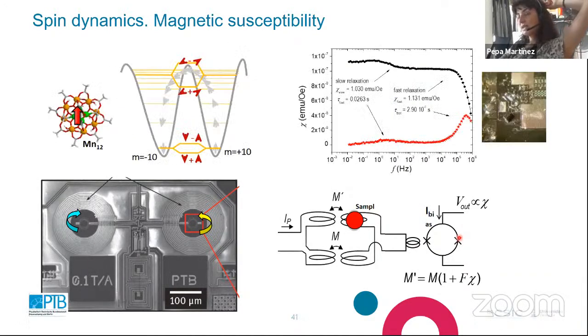Here you can see a very nice measurement obtained with manganese 12. Manganese 12 is the archetype single molecule magnet that you can think of. It consists of 12 atoms of manganese, antiferromagnetically and strongly coupled between them, giving rise to a total spin equal to 10. Here, relaxation can occur at different frequencies depending on some structural properties of the particle.